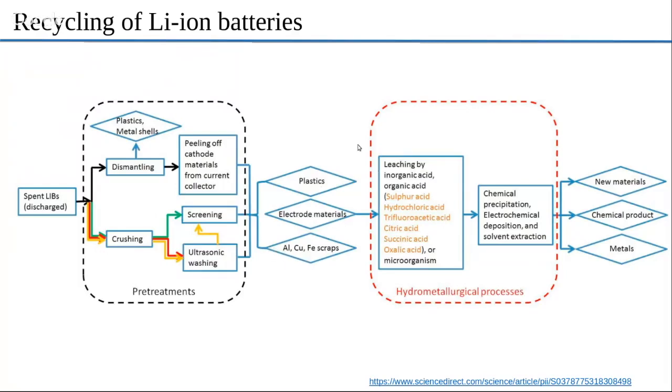Then they're subject to a very vigorous hydrometallurgical and pyrometallurgical. Hydro means you use very strong acids that can leach the material. Basically, you use sulfuric acid, hydrochloric acid, trifluoroacetic acid, citric acid.